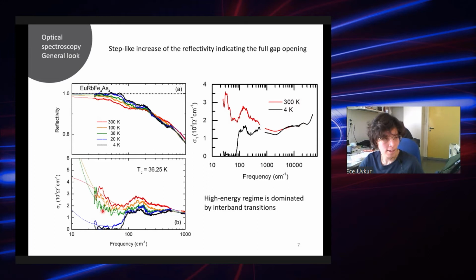But at the end, back then, there were no bigger, homogeneous samples available, and we could actually discuss quite a lot about the superconductivity with the data at hand. So when you look at the reflectivity, the sample is quite metallic. When you look at the high temperature response, the reflectivity increases monotonically towards lower energies, indicating a highly metallic nature of the sample.